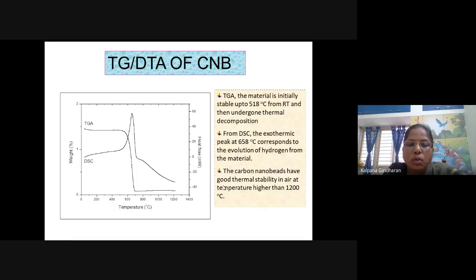From DSC also we have done this. You could see that at 658 degrees Celsius, the peak corresponds to the evolution of hydrogen from the material. So I think this carbon nano beads - I will show you why I'm calling it beads - has good thermal stability.